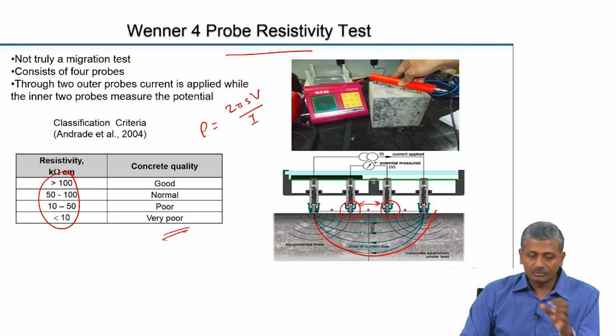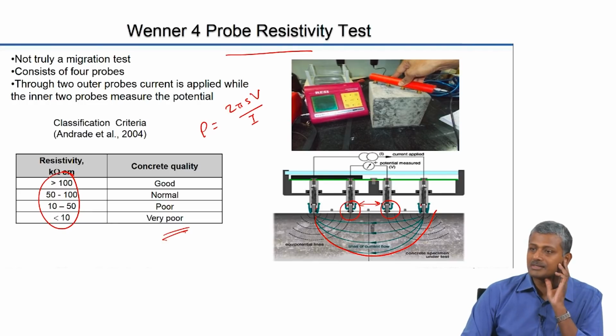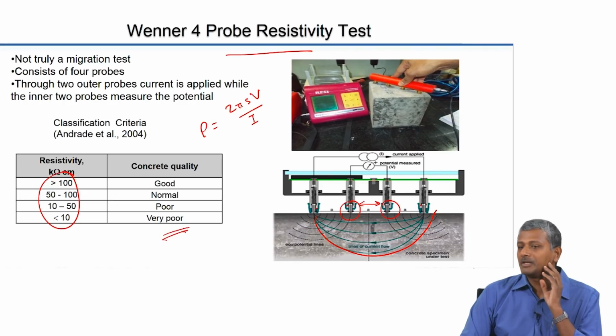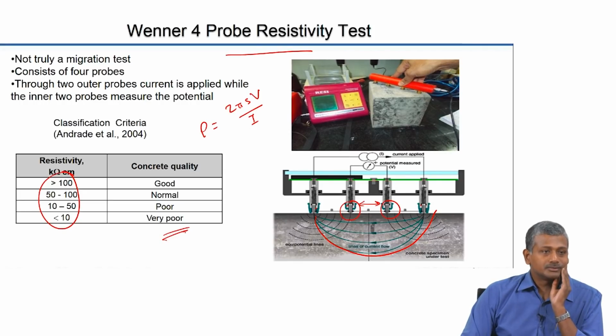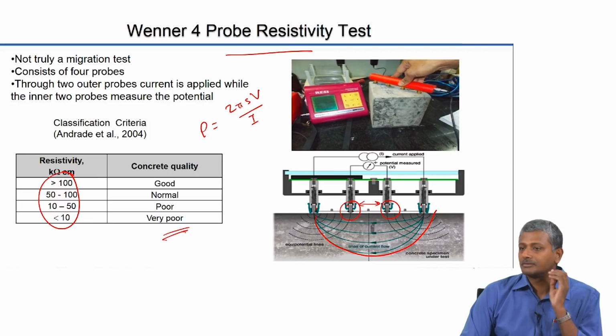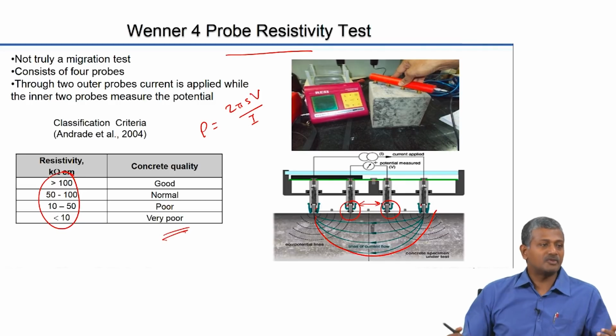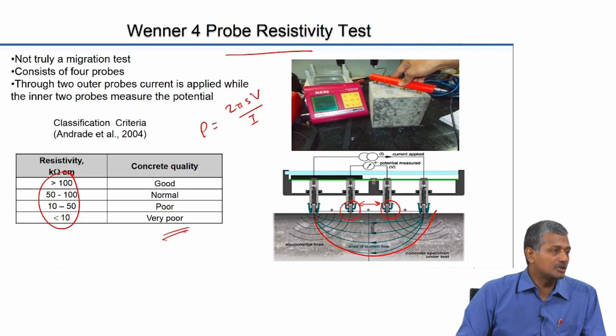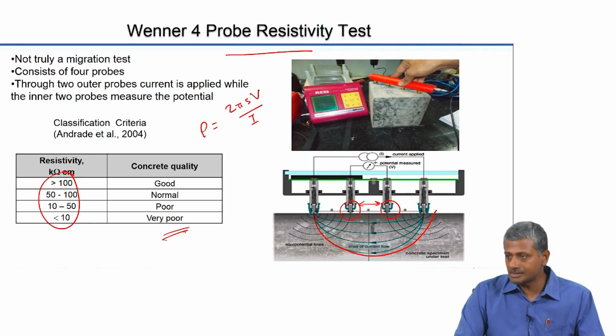But what is one major drawback in this case, in this experiment? Concrete has to be completely saturated. If it is unsaturated, what happens? Obviously, resistivity is going to be very high because of the lack of moisture in the porosity. The porosity has to be filled with water for conductivity to happen, otherwise this experiment will not make any sense.